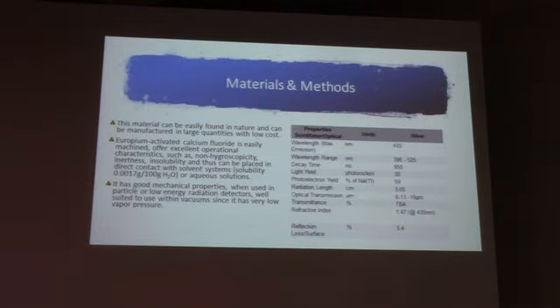So the materials, as I said before, there are a lot of reasons why I chose that. Except the high melting point, the robustness to thermal and mechanical shock is also important, as well as non-hygroscopicity. This kind of crystal's non-hygroscopicity tells us that it can easily be used in direct contact with solvents and aqueous environments, which is very important, especially in marine research. The other reason is that it's quite easily machined, which is pretty important because we have to have it first of all in very specific sizes.